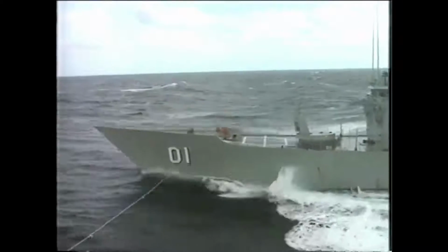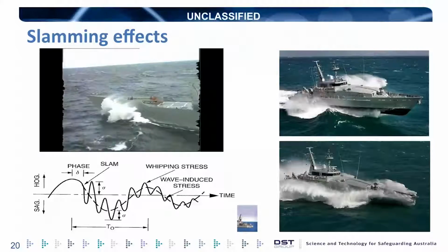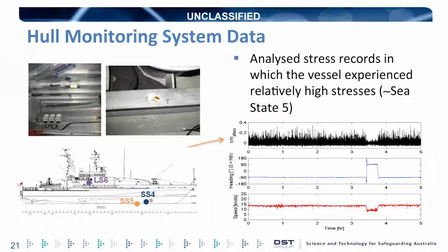So the problem I've got now is each time the bow emerges and hits the water, we get a slam load, and that slam load can excite the resonant frequencies of the ship as well. To investigate this, we've put a monitoring system on one of the Armidale class patrol boats, and there's a number of strain gauges located all around the ship. You can see from the traces over here, these are the stresses on the strain gauge, and you can see here that where the ship's changed heading angle and dropped speed, the response of the ship has dropped significantly, so that will save some of the fatigue life.